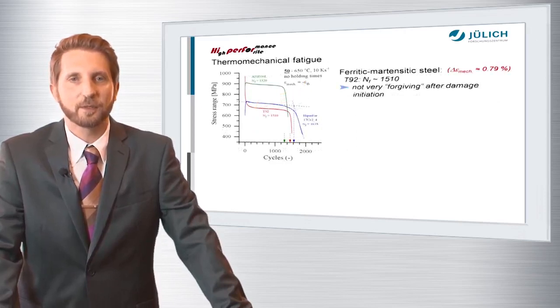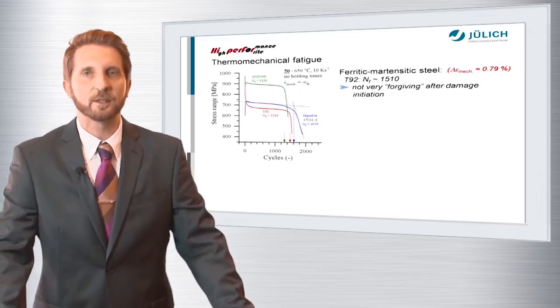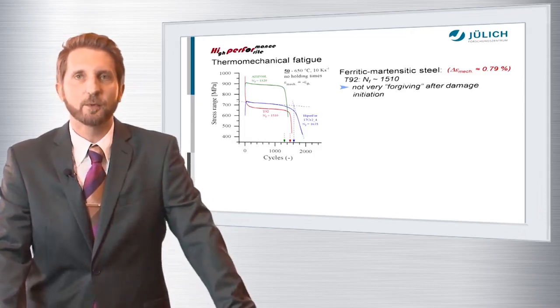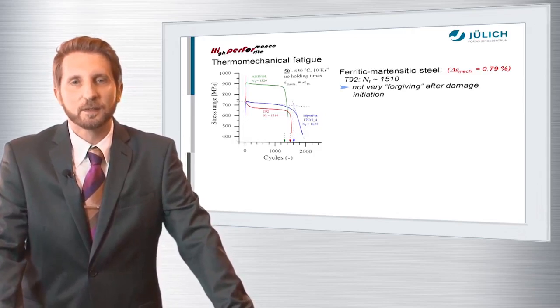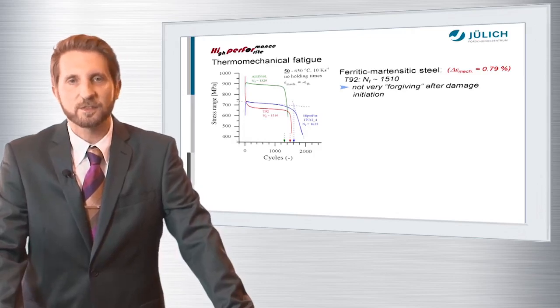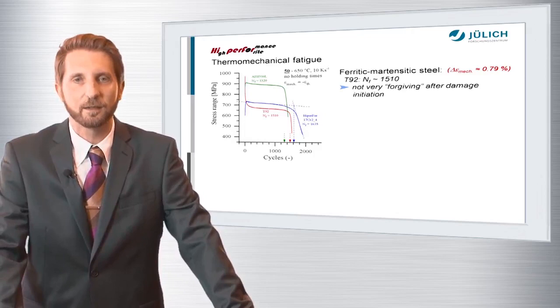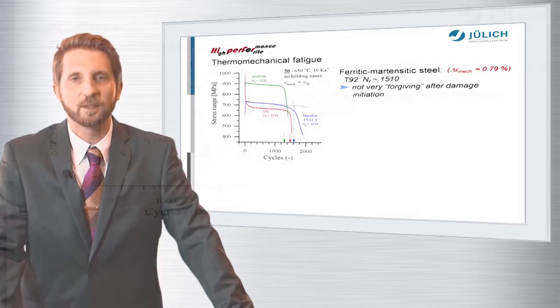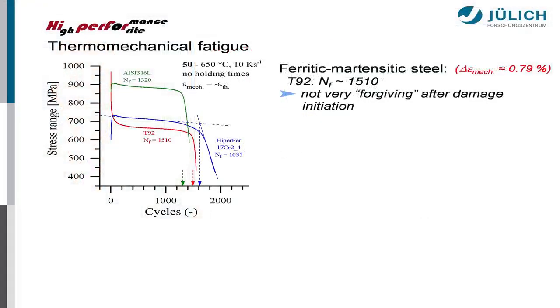In the motivation part, I've been talking about thermomechanical fatigue resistance for cyclic power plant operation. And that is why I brought some data on thermomechanical fatigue. What is done in a thermomechanical fatigue test is you just take a specimen, cycle it through a given temperature range, in this case from 50 to 650 degrees C, employing quite steep heating and cooling rates, in this case 10 Kelvin per second. You do not go for holding times at the minimum and maximum temperatures because you want to restrict creep as far as possible. And in this case, it's a so-called out-of-phase thermomechanical cycle, and that means that the testing machine obstructs the thermal expansion of the material completely.